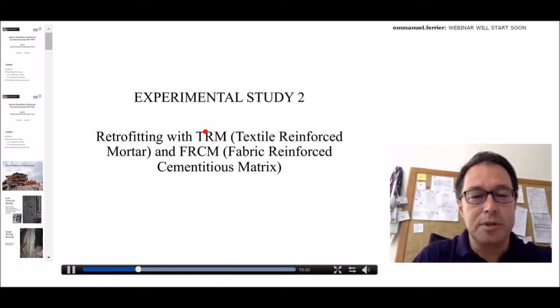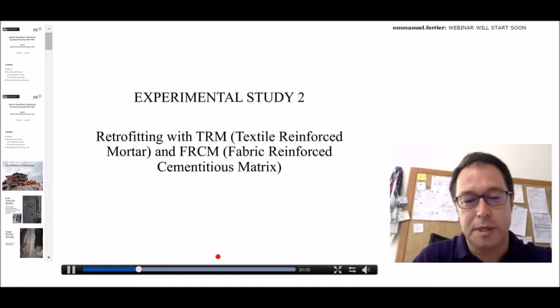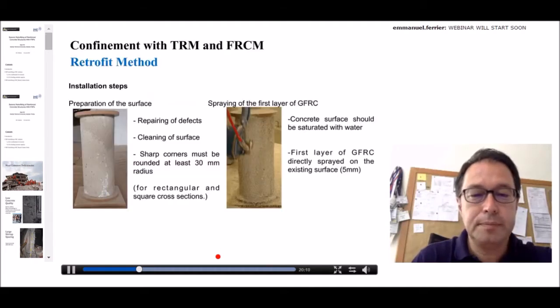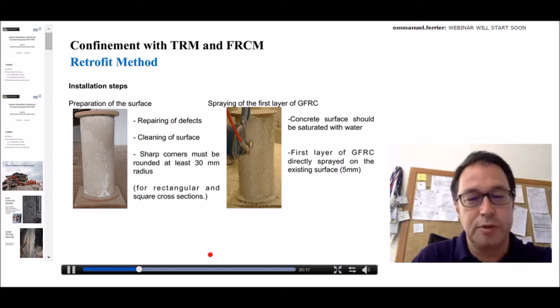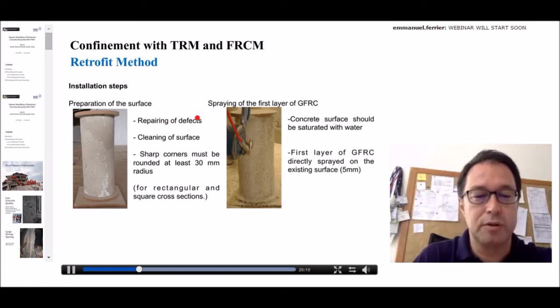So now let's have a look at the columns that we use textile reinforced mortar and fiber reinforced cementitious matrix rather than using carbon fibers and epoxies for the matrix material. Just to introduce the methodology, what we did for the repair and for the retrofit of these kind of columns. This is just showing on small size cylinders, but I'm going to show you the larger size columns.